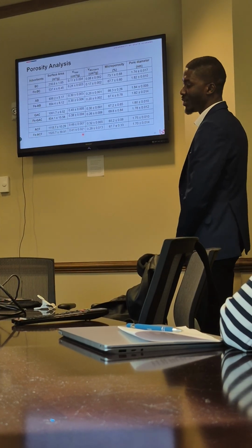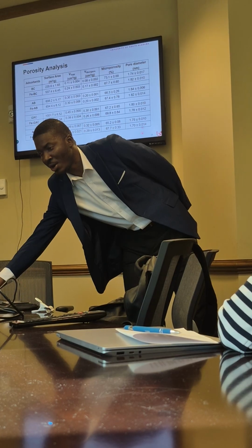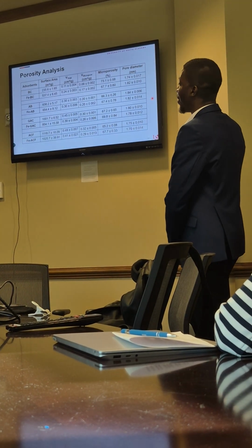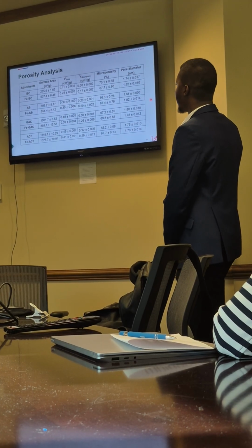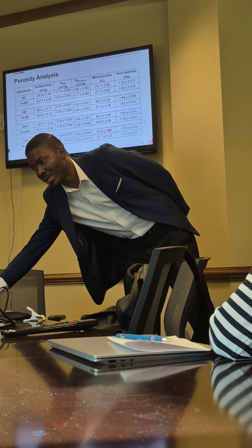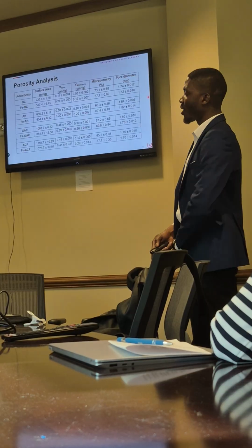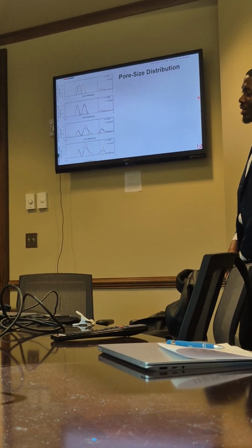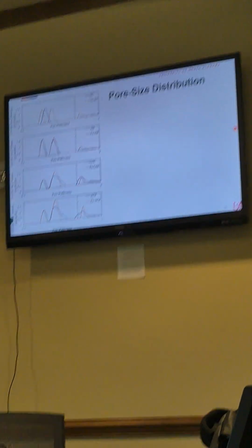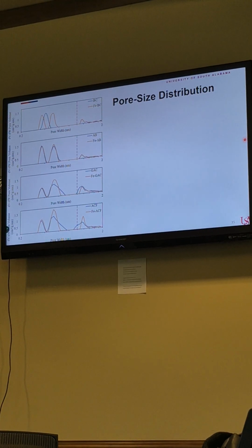micropore area also reduced. Generally looking at our pore diameter, we can see that all our materials are microporous because that is characterized by the pore diameter being less than 2 nanometers. And also we can confirm that with our microporosity, which confirms that all our materials were highly microporous. So to further understand what was going on in the pores, we carried out a pore size distribution. And this was basically done to see how our pore widths look after iron modification.